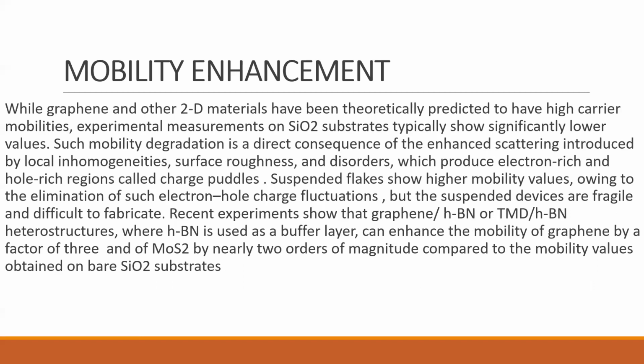Mobility enhancement. While graphene and other two-dimensional materials have been theoretically predicted to have high carrier mobilities, experimental measurements on SiO2 substrates typically show significantly lower values. Such mobility degradation is a direct consequence of enhanced scattering introduced by local inhomogeneities, surface roughness and disorder, which produce electron-rich and hole-rich regions called charge puddles. Suspended flakes show higher mobility values owing to elimination of such electron-hole charge fluctuations, but the suspended devices are fragile